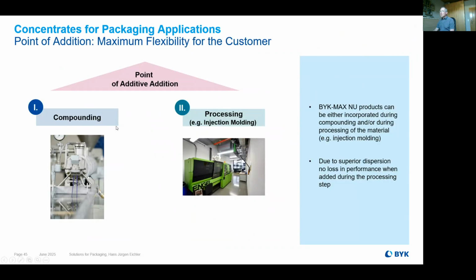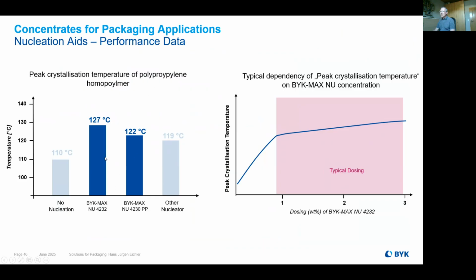So the materials can be used during compounding or also during processing. So it's quite a very general use of the products. And if we start here and look into the processing, you see the 4232 is just a product which has a very nice and high peak of crystallinity. It's with 127 higher compared to that what we have with a non-nucleated material, means you are able to form out quicker your products. The 4230 is quite also nice improvements, but not on the same level like the 4232.